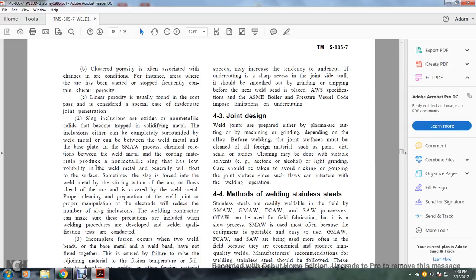They can be completely surrounded by the weld metal, or can be between the weld metal and the base plate in the shielded metal arc welding process. The chemical reactions between the weld metal and the coating materials produce the non-metallic slag, which is lighter than the weld metal, so generally it will float to the surface. Sometimes the slag is forced into the weld metal by the stirring action of the arc. Proper cleaning and preparation of the welded joint, and proper manipulation of the electrode, will reduce the amount of slag.